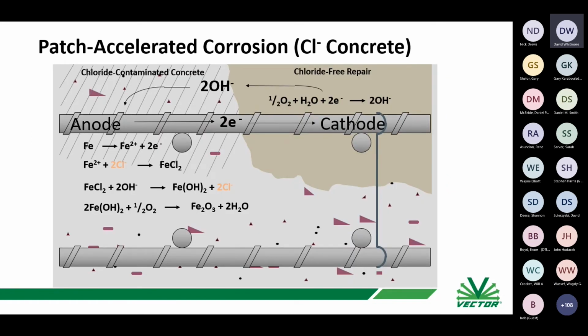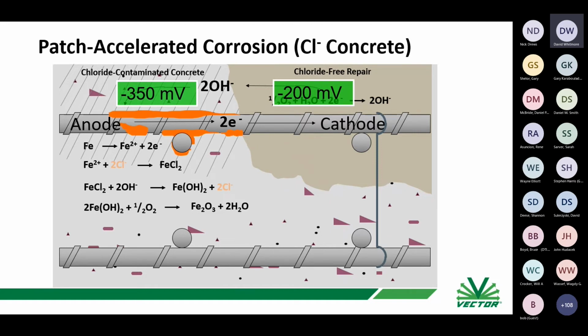Okay, so we've already kind of jumped to this part. If we're repairing a portion of the concrete with chloride-free material, and we're leaving chloride-contaminated material adjacent to it, we're going to create a situation where we have a potential difference between those two areas, and that is going to lead to corrosion that's in a way going to be driven. I mean, it's going to occur anyway, but it's going to be driven worse because now you've coupled it with a material directly adjacent that is more positive than what it was. And you can pick up all of this by doing the detailed half-cell corrosion potential survey type data that you want.